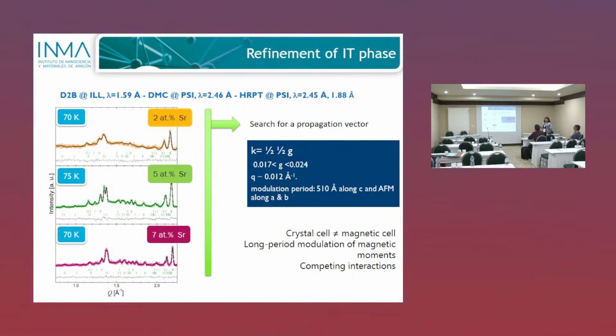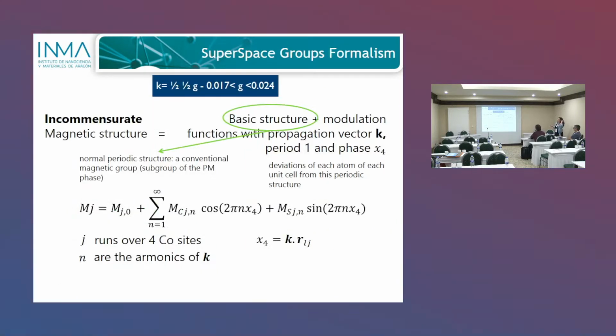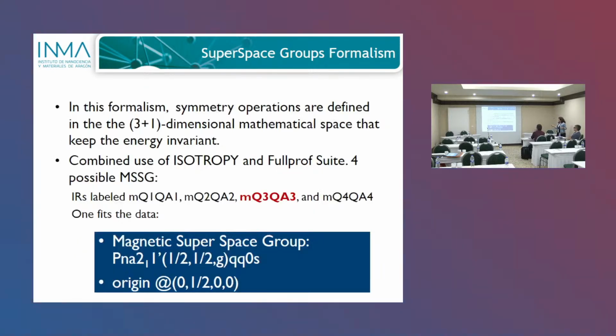But which is the model? You have to find or to propose a model for this magnetic structure, not just a propagation vector. To do that, using neutron diffraction, one strategy when you are dealing with incommensurate magnetic structures, which are the hardest to deal with, is the superspace group formalism, which is very recently implemented in FullProf from 2020. And you think of the magnetic structure as a basic structure with a conventional magnetic group, a Shubnikov group, and you add a modulation function with a propagation vector k, which is the one we found from the data. When you write the magnetic moments at each crystallographic site in this way, then you can inject this into the FullProf program and make a refinement of the directions and the moduli of the magnetic moments at each site. And when we did that, we obtained a model, a magnetic superspace group, which is this one.